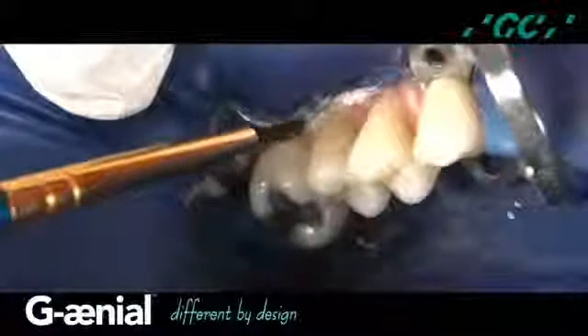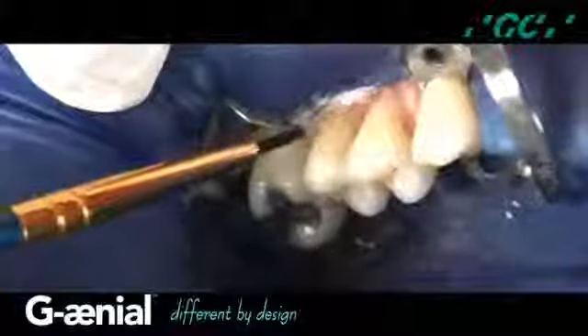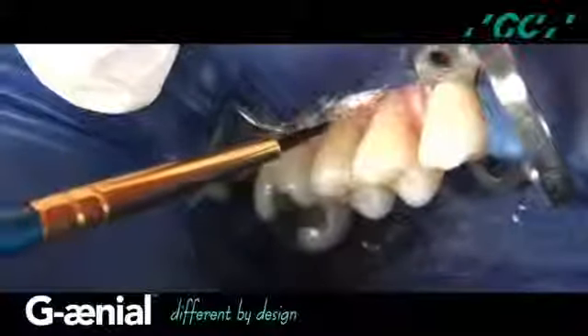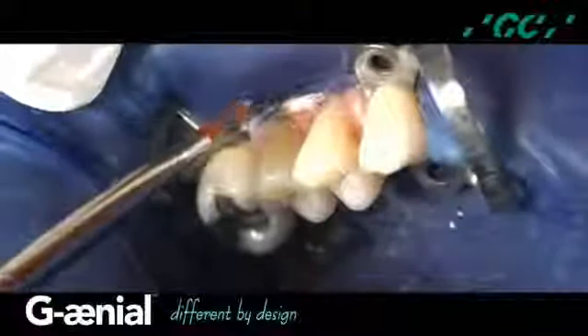By anticipating the required artificial enamel dimension when developing the artificial dentin layer, a final artificial enamel layer of AE shaded G-aenial Universal Flow can be integrated to achieve an optimal anatomical emergence form and color. I use a small amount of composite primer by GC on the tip of the brush. This facilitates adapting and smoothing the flowable material while developing the emergence contour, and it also improves the smoothness of the restorations. And light cure for 10 seconds.